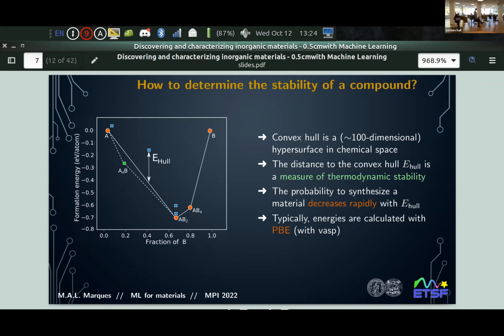So the distance to this line is actually a measure of thermodynamic stability. Obviously we can synthesize unstable compounds. But if you look statistically, it's almost impossible to synthesize something that is 100 meV per atom above this line. If you grab all known compounds and calculate the distance to the hull, I think 95% of them are within 100 meV per atom from this line. And the other ones that are not are probably mistakes: incorrectly determined structures, or structures determined at high pressure but calculated at zero pressure, or something like that.